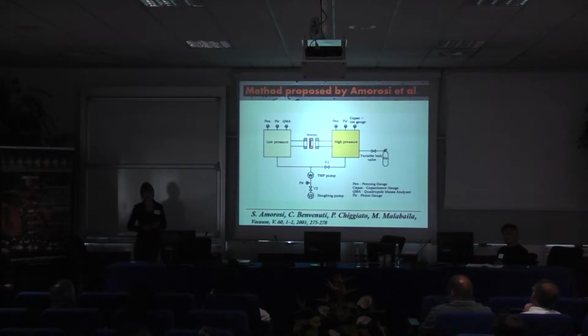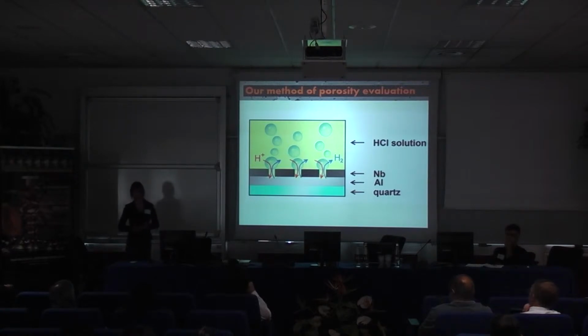But this method is labor and time consuming, and it needs very accurate treatment of the film, because the film can be destroyed when you dissolve copper, when you place it inside the chamber, when you insert helium gas, etc. So we would like to propose here a much faster and easier method of porosity evaluation.